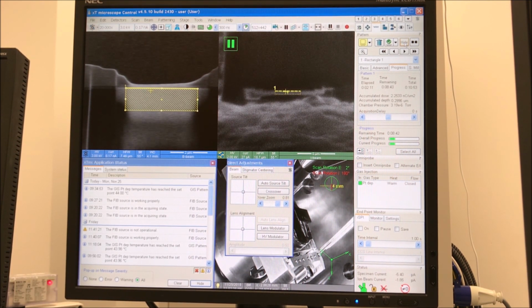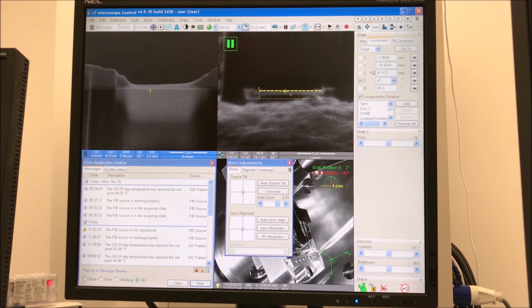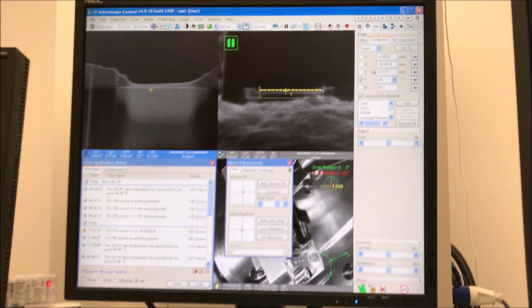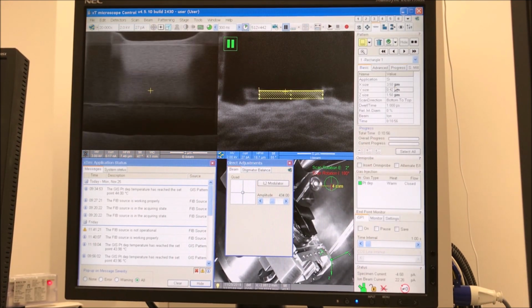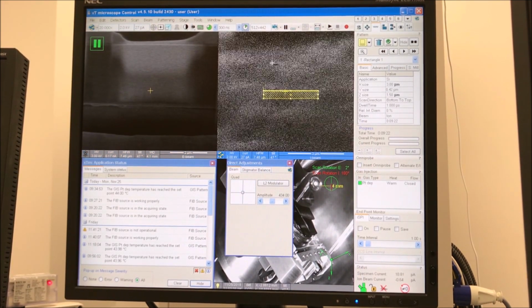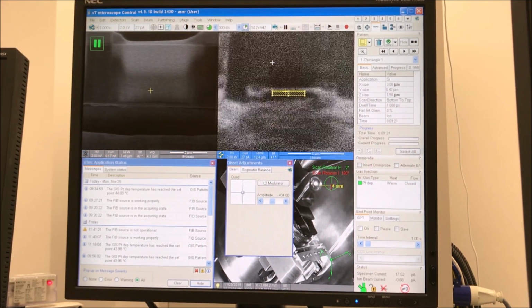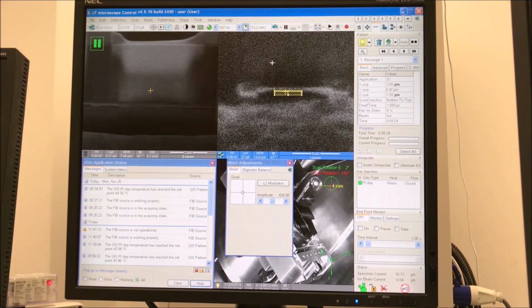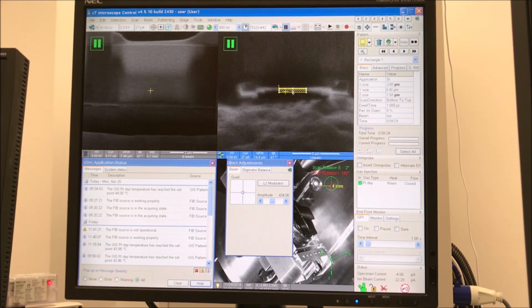So now I'm going to tilt -4 degrees away from normal incidence, move the X dimension of the pattern in a little bit again, and execute one last milling step from the bottom side of the lamella, which again is the opposite side that we're seeing in the E-beam. And then once that's positioned, I'll go ahead and start the pattern, take a snapshot, and then make sure the image is stable, and go ahead and execute.